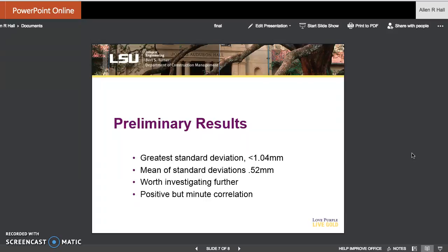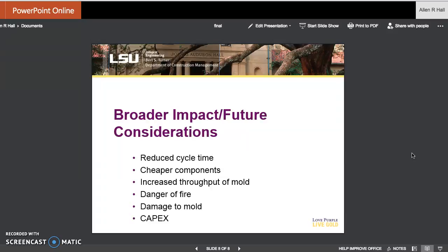But the one positive is that as the temperature was raised, there was actually more spring and curling. Very, very minute, but there was a positive correlation, and I'm actually happy with that because it does show that we were able to isolate all the variables, and the only thing that was changing our results was, in fact, the temperature.